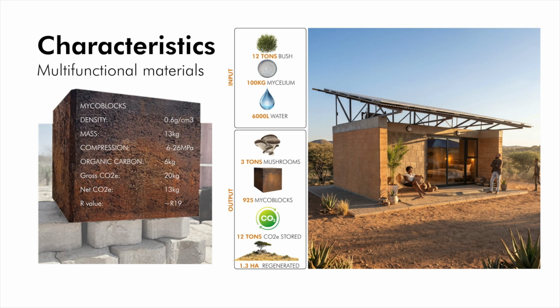So what we did from that is subtract all of the manufacturing processes, the cultivation processes, and the fact that the mushrooms are being digested by people. We're digesting them and breathing them out, unless we're completely turning it into our own biomass, which would be dangerous. We're mostly respiring that carbon back into the environment. So we don't count any of the mushrooms. It's really just the spent mushroom substrate that gets locked into building material and isn't burned and doesn't release that carbon dioxide into the environment. It ends up being about 1-to-1. Every ton of material we make, we store a ton of carbon dioxide.